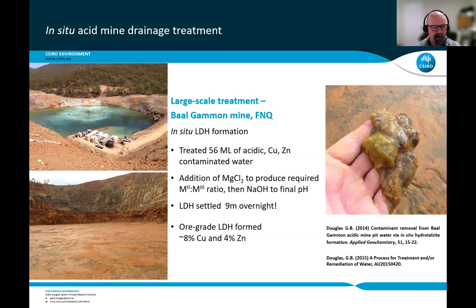We needed to add magnesium chloride, and in the top left slide, if you look really hard, you can see a circular image on the top of the pit. That's actually a sprinkler on a pontoon where we're irrigating the pit with the magnesium chloride. You can see 2 different colors: the green where we've added the magnesium chloride and we're forming copper chloride, and the bluish areas that we were yet to treat, and that's still the copper sulfate, so that blue versus the green color. Now, what we did after that was we added sodium hydroxide and we took that up to final pH. Once we did that, we had spontaneous formation of the layered double hydroxide.